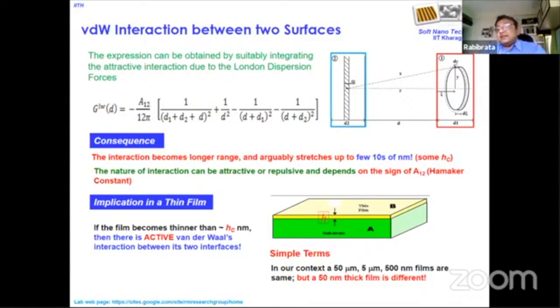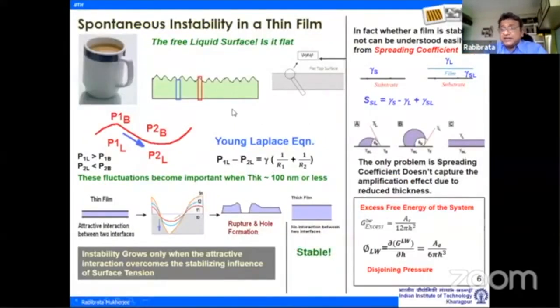Please do understand that if you are talking about a liquid film, the surface of a liquid film always has fluctuations because of the internal kinetic energy of the molecules. Even if you look at the surface of a bucket of water, there are these fluctuations, but nothing happens. The moment there are some fluctuations, surface tension, or the so-called Laplace pressure, flattens them out, and that's over. But when you are talking about an ultra-thin film with these fluctuations on the surface, you need to understand that there is a local variation in the film thickness, and as a consequence, the strength of the disjoining pressure changes from point to point.